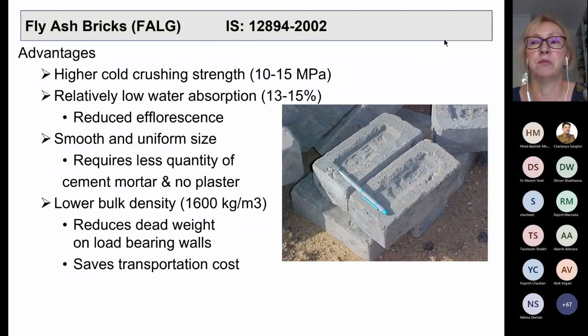In conclusion, from the clay bricks, I would like you to know what is the class of bricks and what is the minimum allowable grade in India. Fly ash bricks are specified by the standard which I listed at the beginning, IS 12894. They have higher crushing strength or compressive strength compared to clay bricks. Normally, 10 to 15 megapascal strength can be easily achieved, and they have relatively low water absorption. They have reduced efflorescence, although efflorescence is possible also with these fly ash bricks.